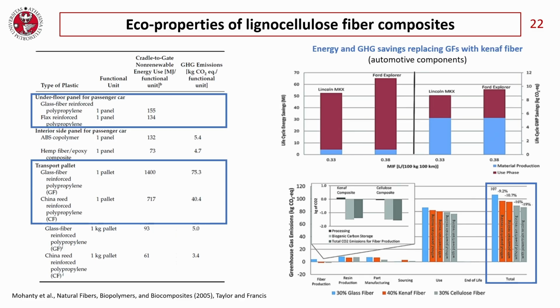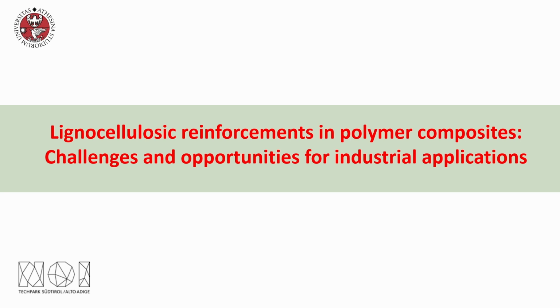If we compare, for example, an underfloor panel for automotive application, if you prepare it with a flax reinforced polypropylene instead of using glass reinforced polypropylene, you have an important non-renewable energy saving at the production. The same if you consider other kinds of automotive components like this. And here I reported another example. If you replace the material with 30% of glass fiber with 40% of kenaf fiber, you can see that you have a reduction of the greenhouse gases emission of 10–15%. So I hope that I convinced you that this material could be a good alternative for many industrial applications, but now it's time to leave the floor to my colleague Giulia Freddi that will explain and show you the challenges and industrial opportunities for this material.